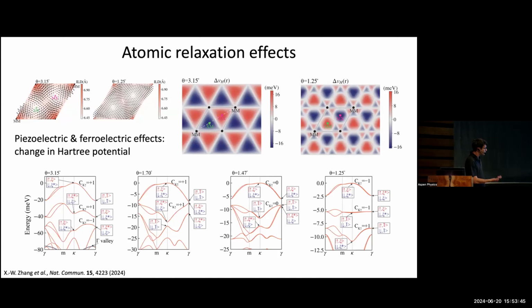And so after our result, actually, as you saw, the twisted homobilayers were predicted to be topological over quite a broad range of twist angles, and we certainly don't see that. But taking into account these atomic displacements, in a calculation done with the benefit of machine learning, they found Chern numbers of the bands that were twist dependent and consistent with our results.